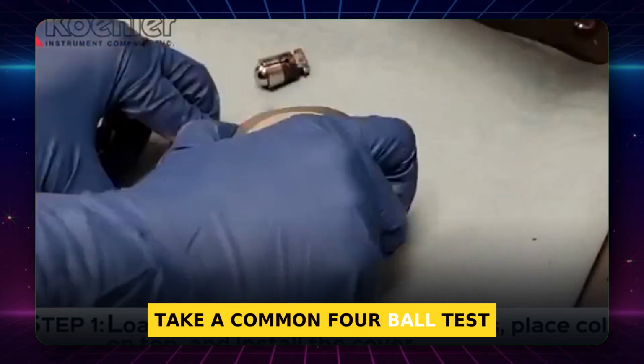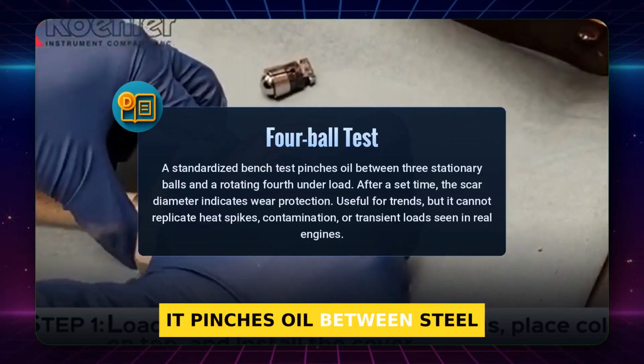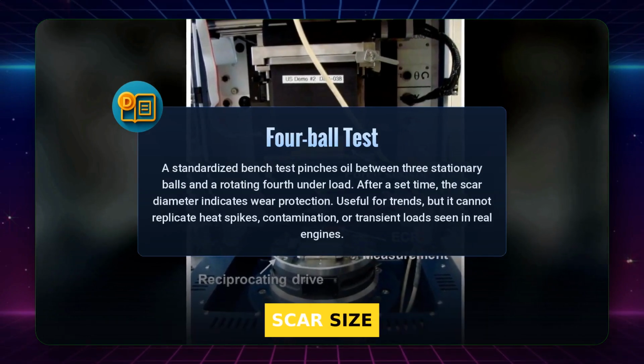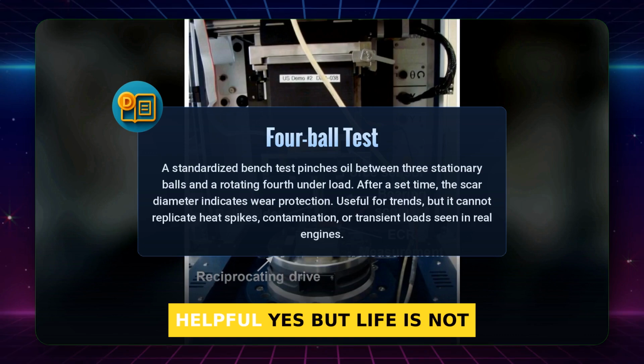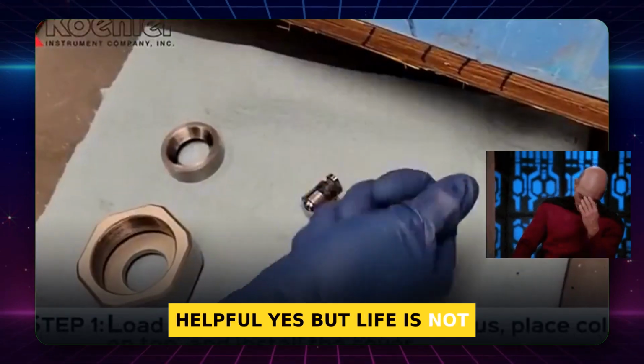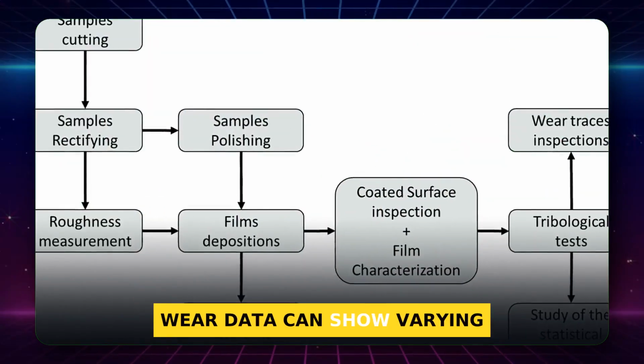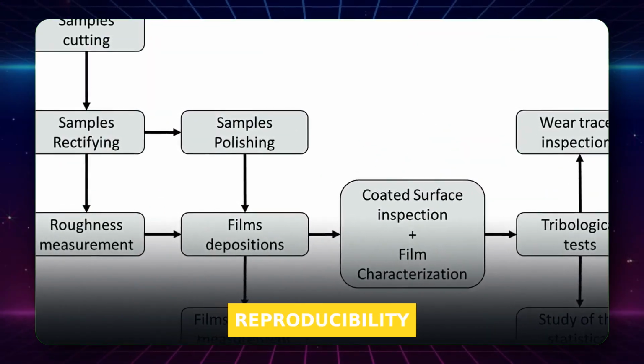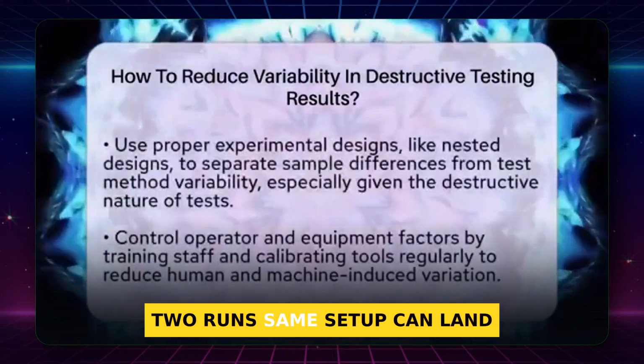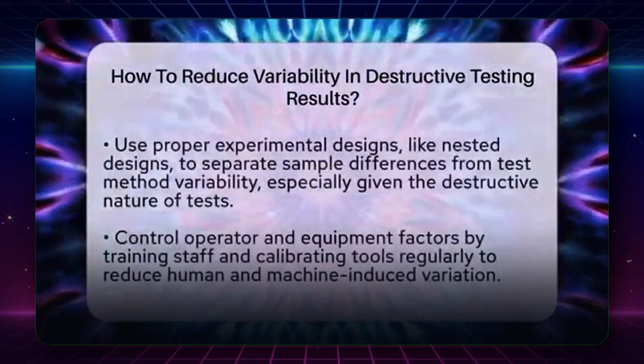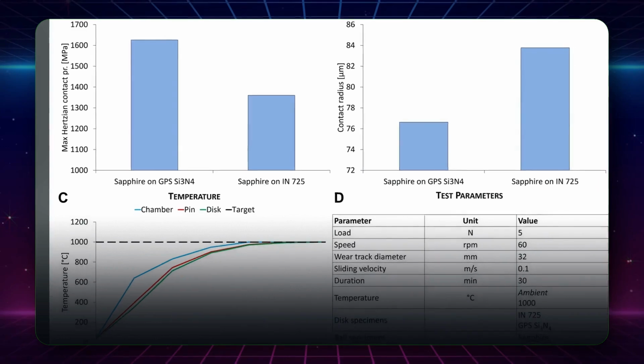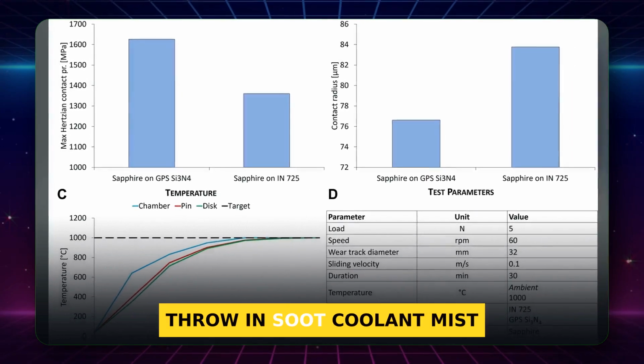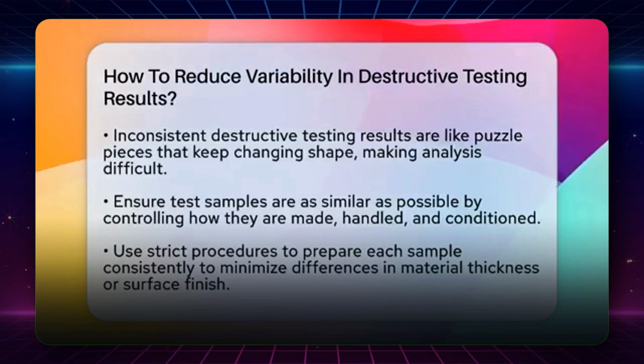Take a common 4-ball test. It pinches oil between steel spheres and reports a wear scar size. Helpful, yes, but life is not a steady pinch. Even researchers note that wear data can show varying repeatability and reproducibility. 2 runs, same setup, can land a different number. If that is true on a bench, imagine the spread when you throw in soot, coolant mist, or cold starts.